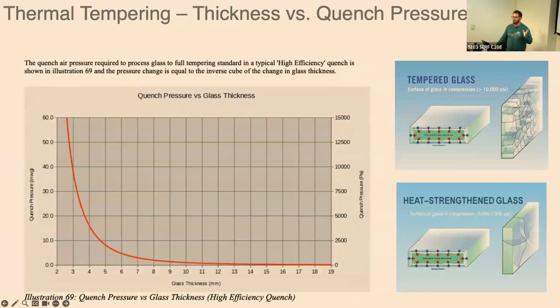Right around 2 millimeters, you come around the theoretical limit of quenching. For those of you who weren't at the talk, this is the quench pressure versus glass thickness curve, with the drive from 3.2 to 2.5 to 2 millimeters. The way thermal tempering works is you heat up the glass, freeze the surfaces, it shrinks in the middle, and it pulls the surfaces into compression. You need a certain amount of thermal mass to pull the surfaces into compression, so it gets harder and harder to do. Your quench pressure has to go up and up for thinner modules. This is why it doesn't work with the thin glass John mentioned.